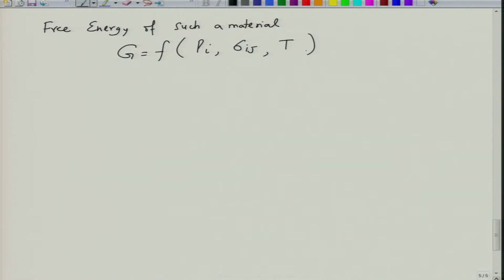Okay. And then free energy is also affected by the electric field. Polarization is generally what we measure after applying an electric field. Stress is something which you can apply or measure after application of an electric field or application of strain, then you have thermal response. So, basically when we apply an electric field we can measure polarization, when we apply stress we can measure a strain or vice versa, and similarly when we apply an electric field we can measure a stress, or when we apply stress we can measure the polarization and so on. So, this is how these properties are coupled.